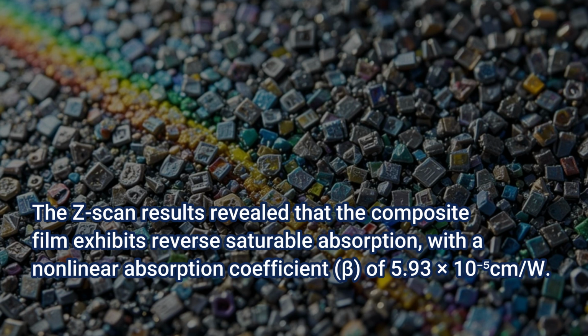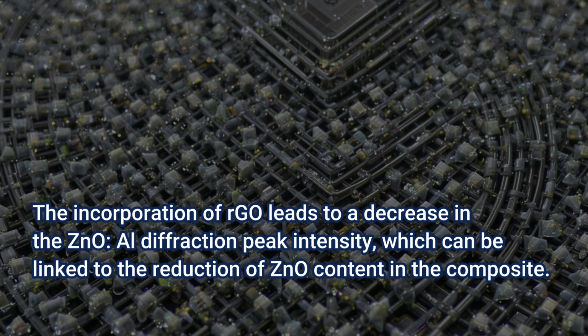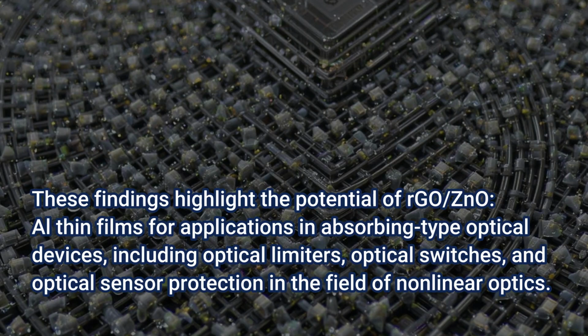times 10^-5 cm/W. The incorporation of rGO leads to a decrease in the AZO diffraction peak intensity, which can be linked to the reduction of AZO content in the composite. These findings highlight the potential of rGO AZO thin films for applications in absorbing type optical devices, including optical limiters, optical switches, and optical sensor protection in the field of nonlinear optics.